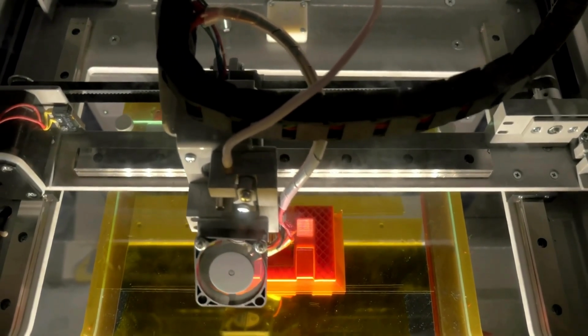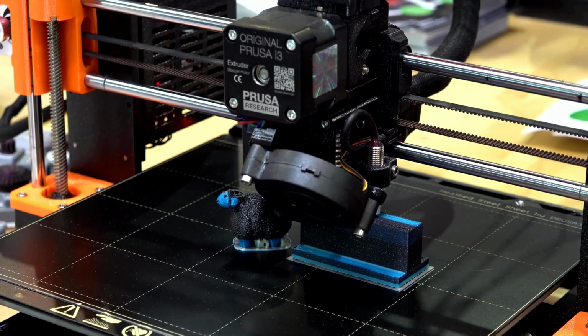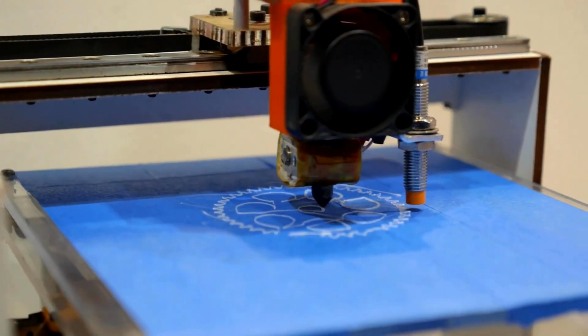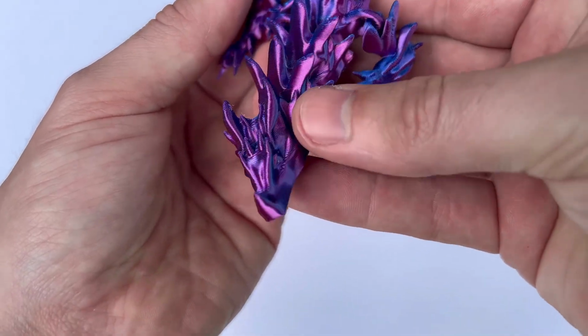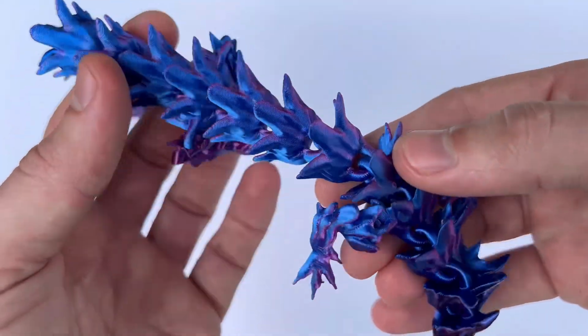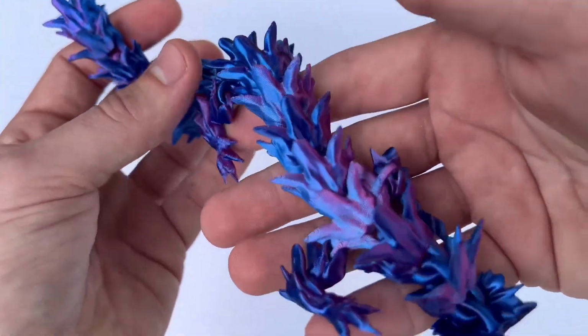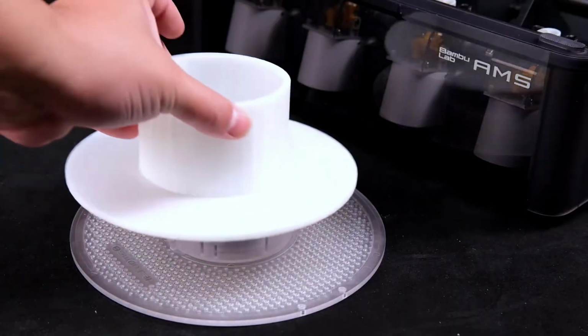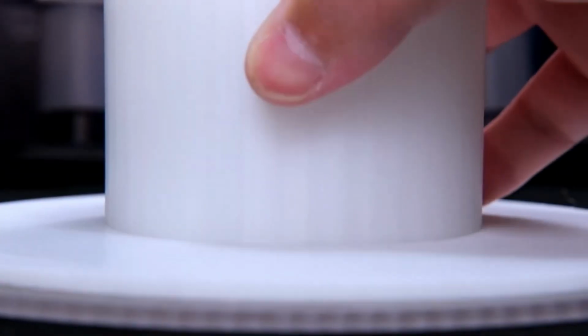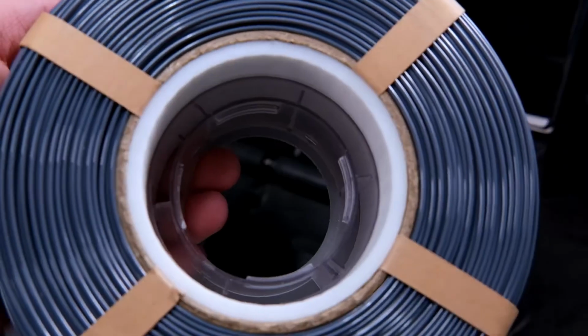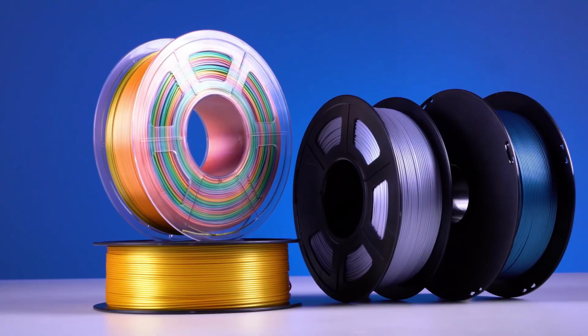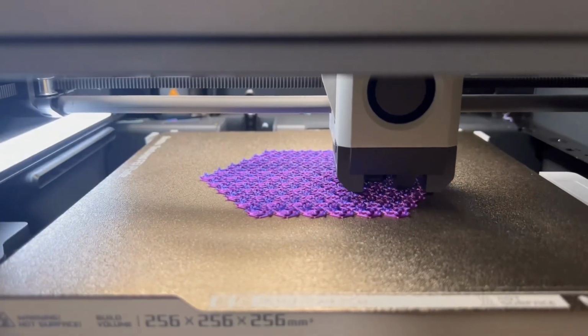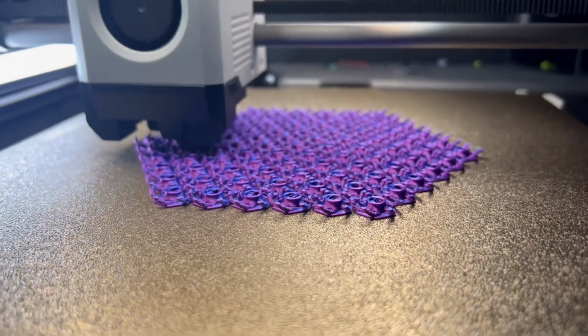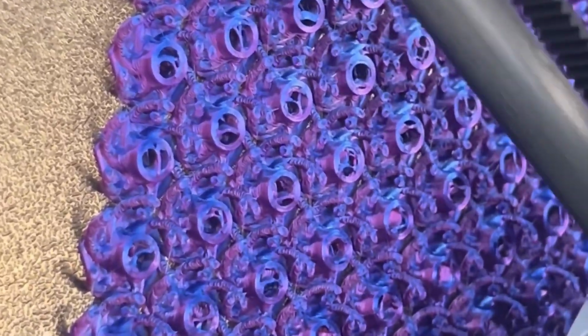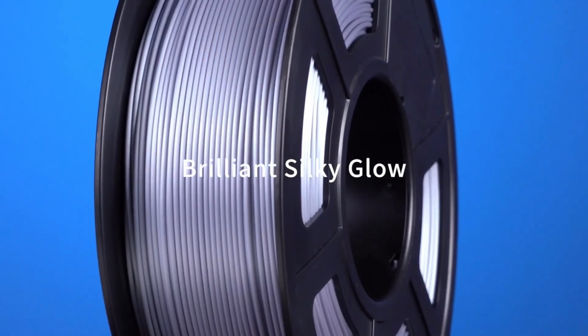Then another huge difference between all of these filaments is the temperature resistance. PLA has a lower glass transition temperature, typically between 50 to 60 Celsius, which means it can soften and deform at relatively low temperatures. PETG has a higher glass transition temperature, around 70 to 80 Celsius, allowing it to withstand higher temperatures better than PLA. This makes PETG more suitable for parts that need to endure warmer environments. ASA has a high glass transition temperature, around 105 Celsius, making it the most suitable for parts exposed to high temperatures. Its UV resistance also makes it ideal for outdoor applications.